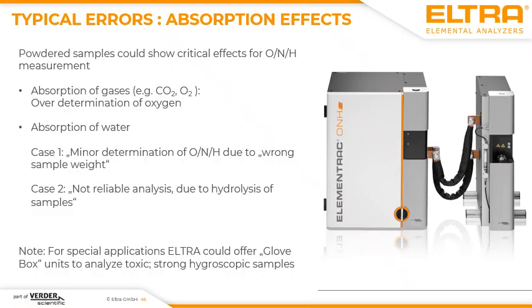On the one hand, you may just have a small determination error due to a wrongly taken sample weight, but especially for battery samples, it could happen that you have a strong hydrolysis of the sample, which means a complete change of the chemical composition of the sample. When you are in charge of analyzing such hygroscopic samples, please contact ELTRA again. Like for the ELEMENTRAC CS, we can offer you special configurations for oxygen-free and hydrolysis-free application because we can place the combustion unit in the glove box.